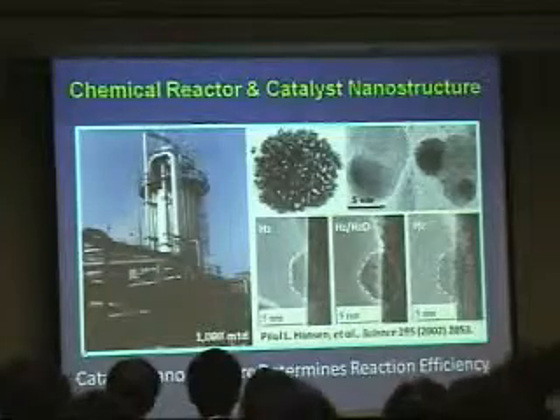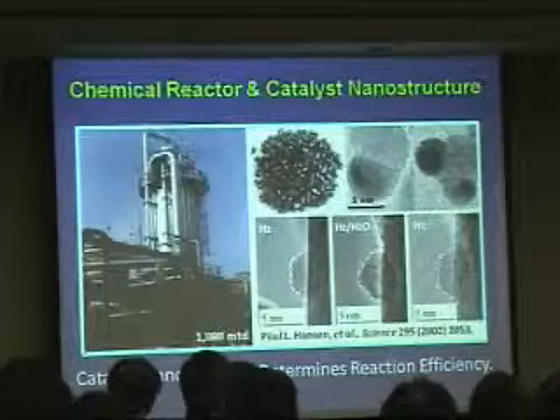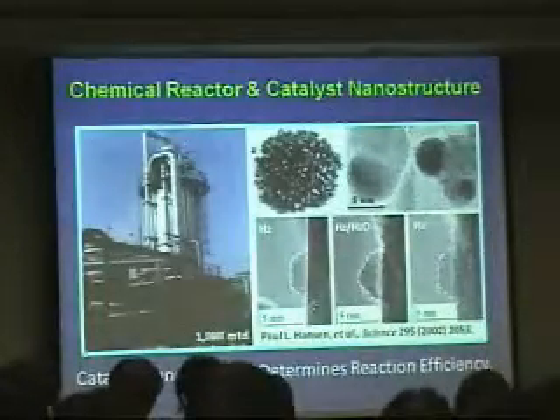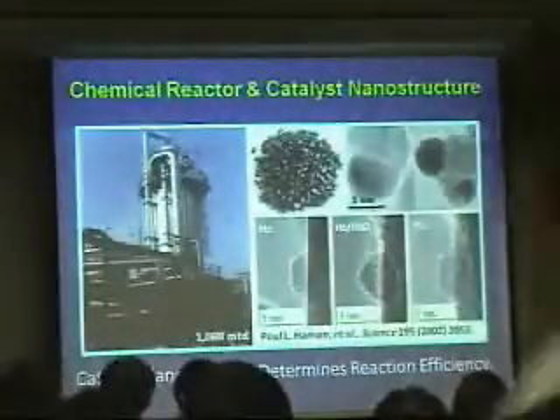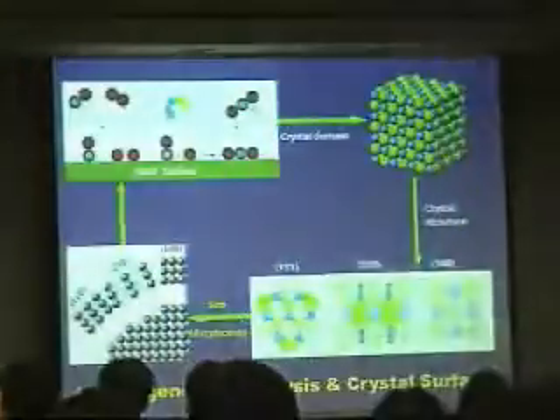And in the early 2000s, about 2002, some people went into more detail and found that the efficiency of this catalyst is largely dependent on the nanostructure. That means a very small nanoscale, like 5 nanometers. Under reaction conditions, or close to reaction conditions, with some temperature and atmosphere, you can find not only the size but also the shape of these copper particles changing. Another question is how about the zinc oxide? It should also respond to the variation of copper particles under the reaction conditions. And this is the start of nanocatalysis.